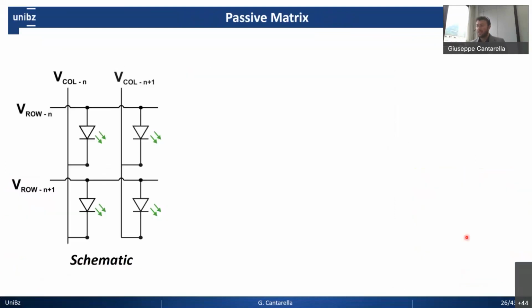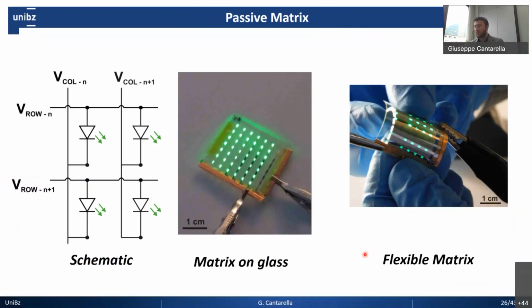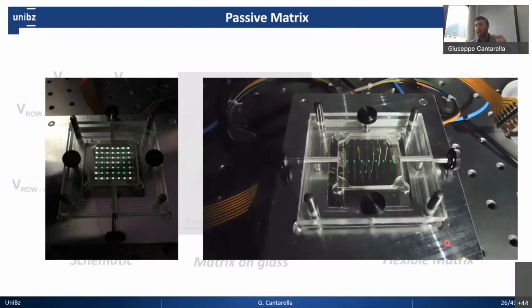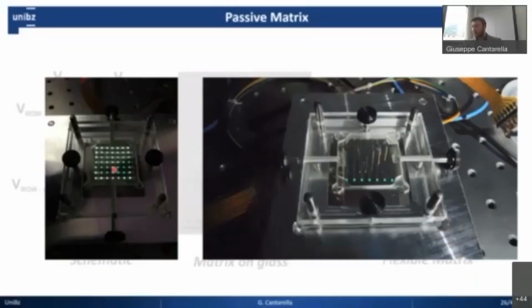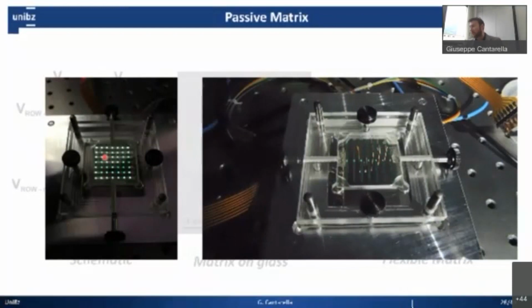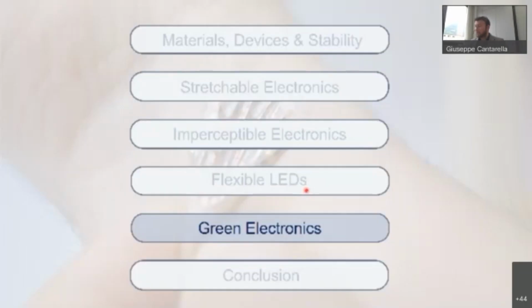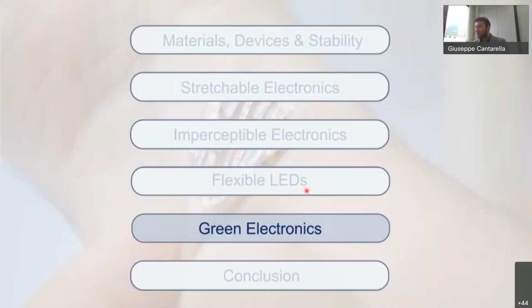We also went for passive matrices, so for systems considering an array of 7 by 7, and the results that you see here are the matrices, these passive arrays, both on glass substrate but also on flexible substrate. And the idea is that in principle we could achieve a yield of 100%. So all the 49 LEDs were perfectly functional, and we could even selectively activate the line that we want. So this brings me to the green electronics. These are the latest results that my group and I achieved.